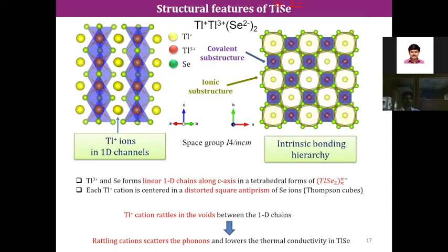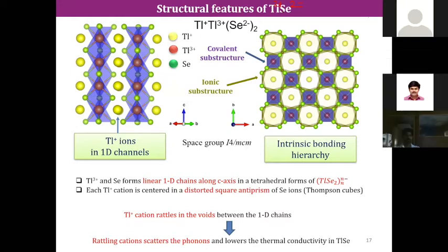Okay, so that we can do by calculating the phonon dispersion. You can see this is the real phonon dispersion, and the first 3 modes are acoustic modes, as I told you from the cartoon, and these are the optical modes. The modes coming from 0 are acoustic modes, which actually carry the heat, and these optical modes interact with the acoustic modes. This is called optical acoustic coupling, and these modes come from the rattler thallium plus 1. If you do the mode analysis by atom projected phonon density of states, you can see that the Eg modes from the blue atom come from thallium plus 1. So basically we indirectly prove, or directly give support, that this thallium rattling is happening, which gives rise to low energy optical phonon modes. And we have a very high Grüneisen parameter, which tells that the system is highly anharmonic.